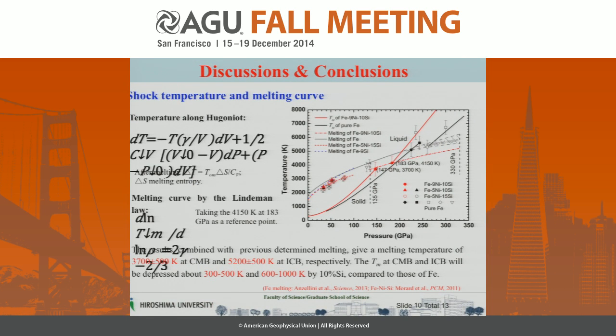Because the shock wave will increase the sample temperature, temperature is also a very important factor. So we have calculated the shock temperature and extrapolated the melting temperature to the melting core. This solid curve is our calculated shock temperature, and this dotted curve is the extrapolated melting curve by the Lindemann law. Compared with the previously determined melting curve, this gives a melting temperature of about 3,700 Kelvin at the core-mantle boundary and 5,200 Kelvin at the inner core boundary, respectively.